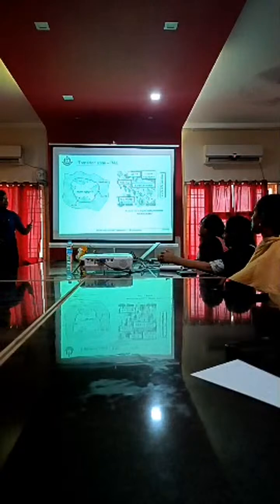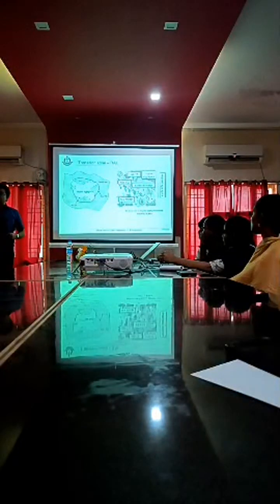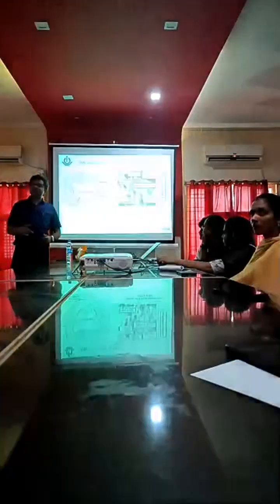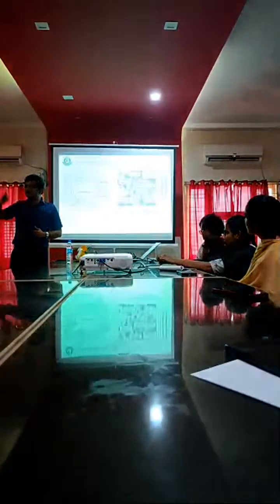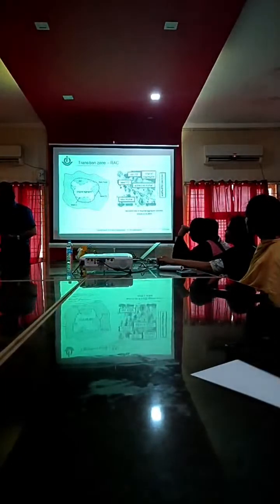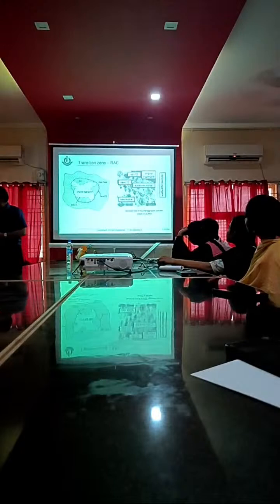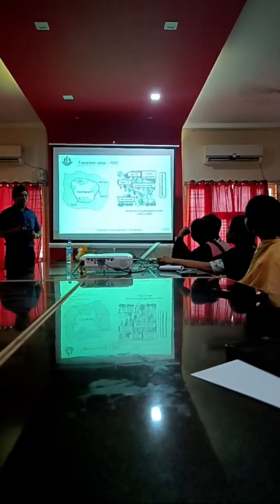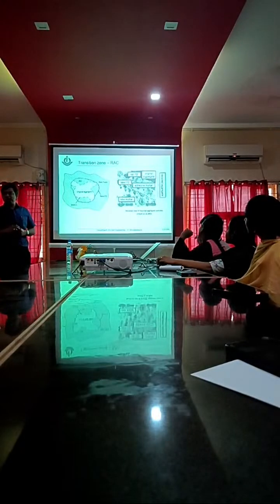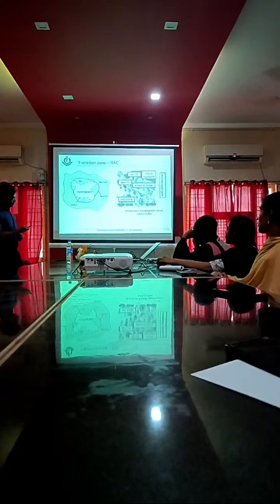In the case of concrete with fresh coarse aggregates, we have only one ITZ. But in the case of recycled aggregates, you have two ITZ. We have the old ITZ, and once you make a new concrete, the new concrete forms another new ITZ. So you have two ITZ zones here. That's the challenge of recycling. That is what I want to convey.